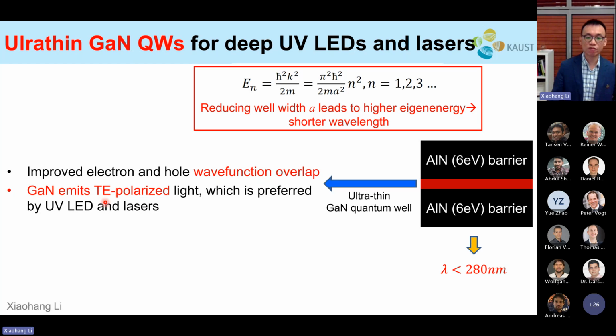This is actually preferred for UV LEDs because you can get a higher light extraction efficiency compared to TM polarization, and also the TE light is more focused compared to the more dispersed TM polarized light. So that is good for optical confinement as well.